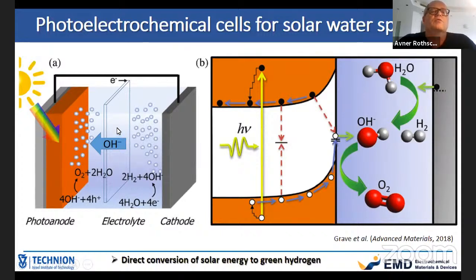So this reduces the number of choices, material choices, and basically most of the materials that survive this environment are semiconducting metal oxides such as titania, iron oxide, etc. If you look more closely at what really happens here, you have an energy diagram with the conduction band and the valence band, and you see photons absorbed, exciting an electron from the valence band to the conduction band. The holes diffuse to the surface where they react with water to generate oxygen, and then the electrons go by the external circuit to the cathode where they generate hydrogen.